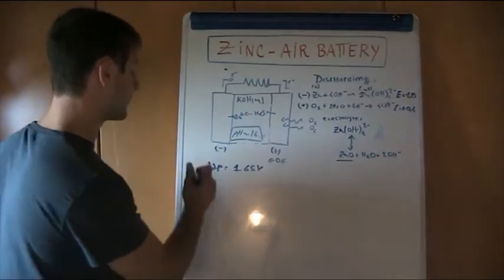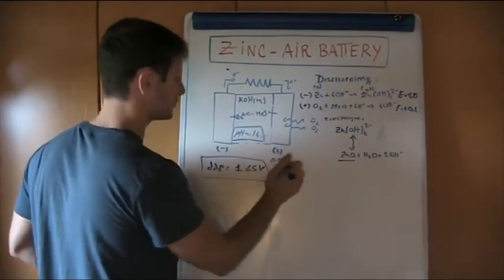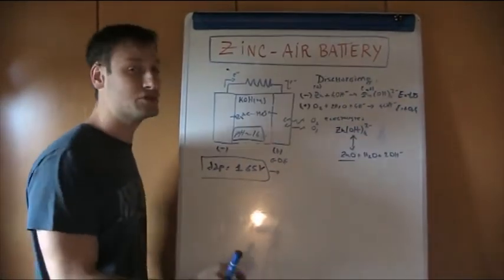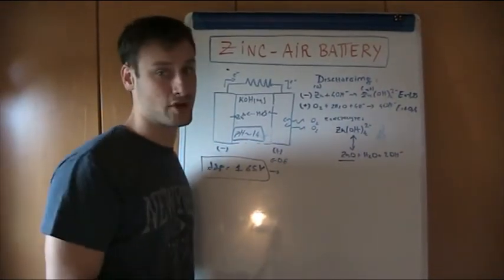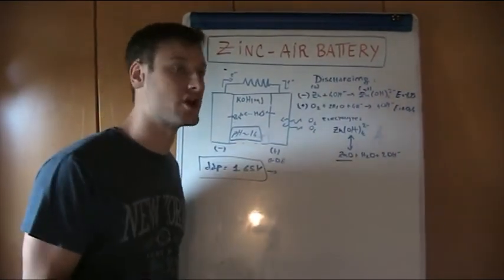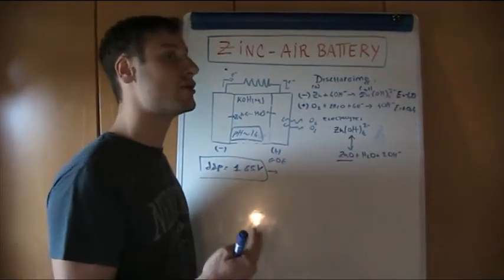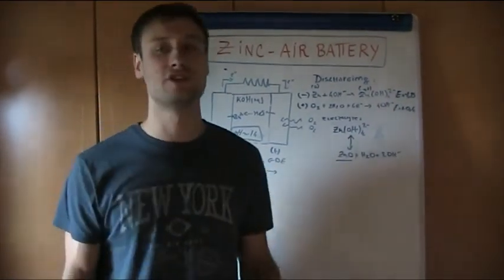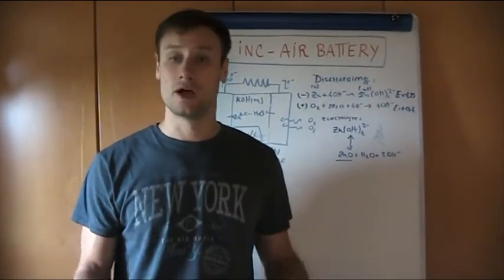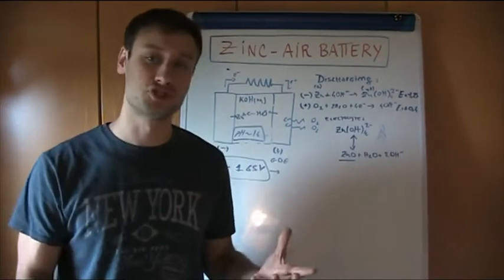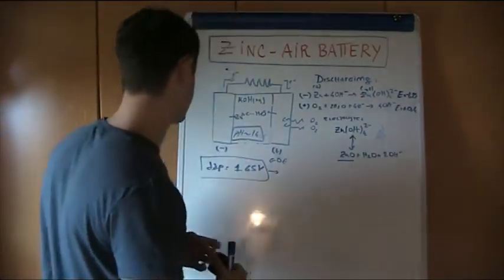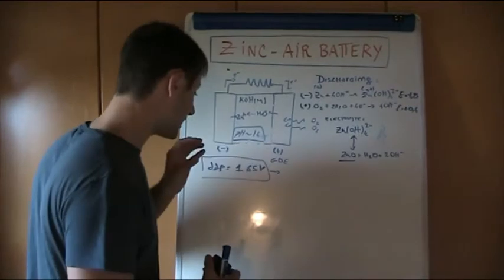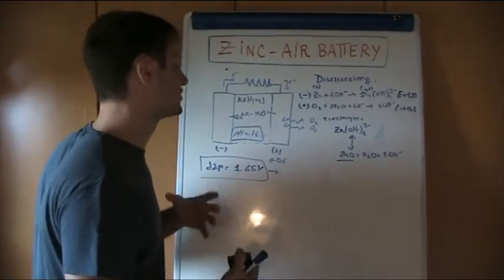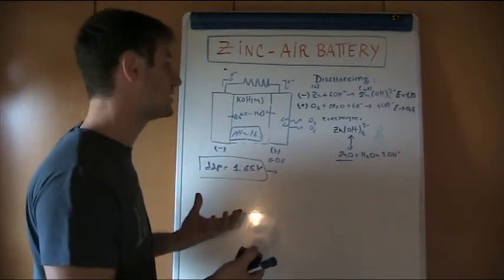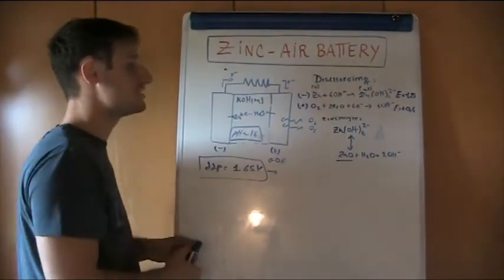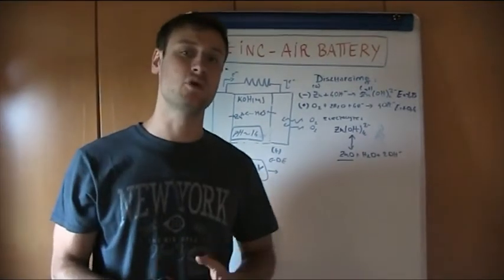Obviously, this is only the theoretical one, the one calculated from the reduction potentials, the potentials of the Nernst equation. But we know that the potentials of the Nernst equation are basically potentials in an open circuit condition, and so we are not considering the overpotential. If we take into consideration the overpotential, some energy is lost, because the energy that we can discharge on the resistance is decreased. The useful work is decreased if we are running a current.